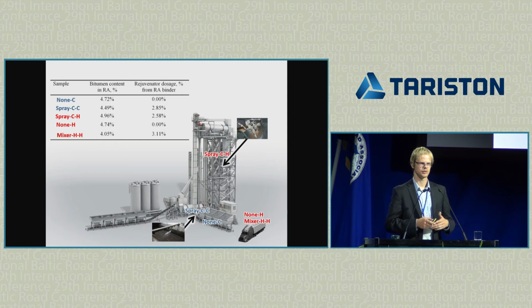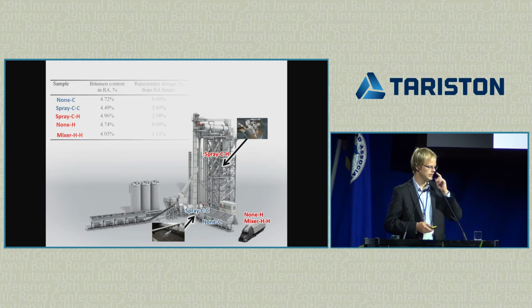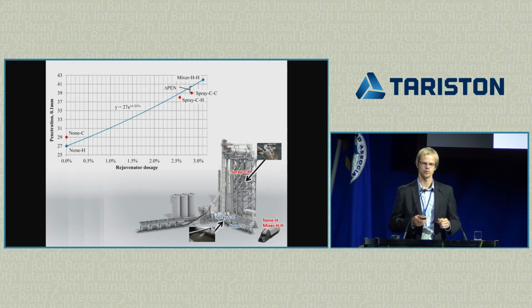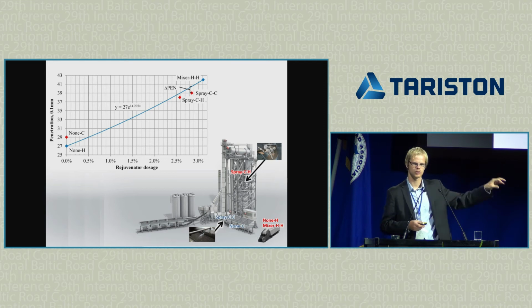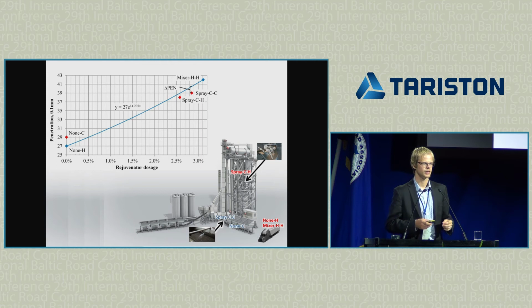That would be fine for an actual production process, but since this is a research study, I had to somehow take this into account. So what I did is I took my samples that were sampled hot, the one without any rejuvenator, and the one where I added the rejuvenator in the mixer, and these are kind of the baseline. So I know that these are the same. The only difference is that the rejuvenator content is different. For one of them it is 0, for the other it is 3.11%.